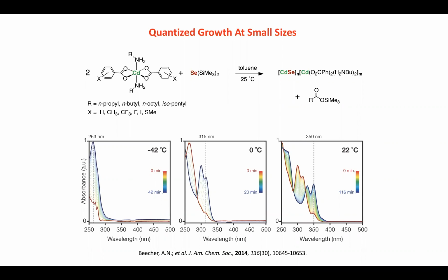This reactivity here is the silicon transferred to carboxylate, and the result is some cadmium selenide containing object that is a strong absorber. And then that material, if you let the solution warm from this frozen toluene up to an ice bath, you'll watch this stuff go away and a new material appear. And again, this new material, if you warm it to room temperature, will disappear and a new crystal will appear.